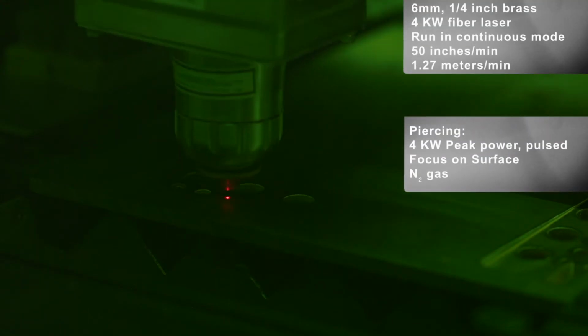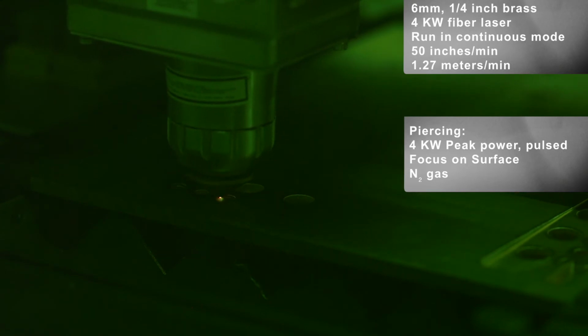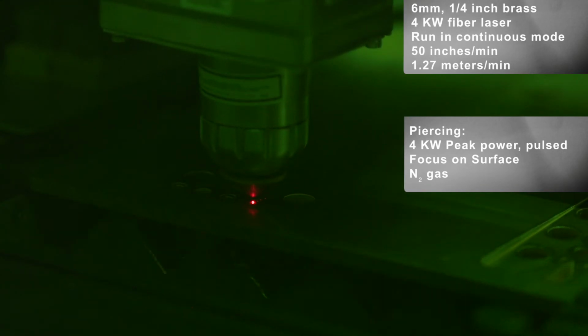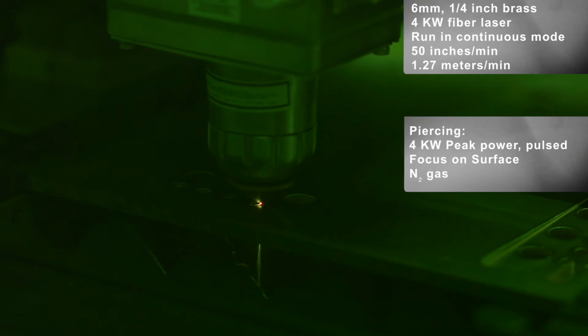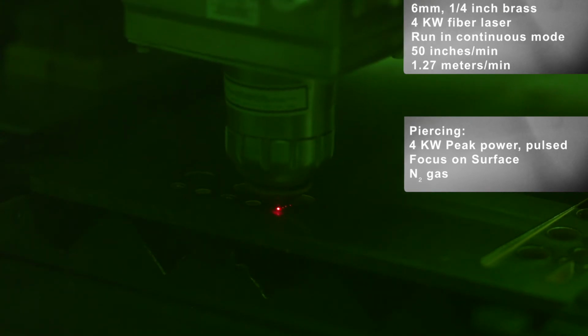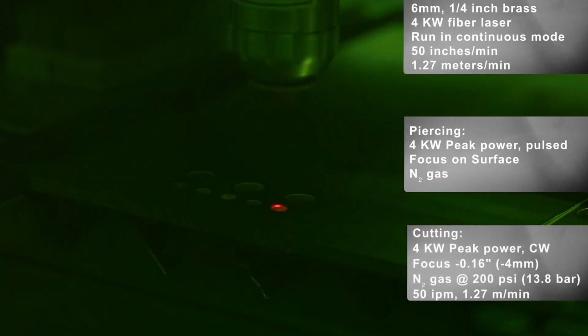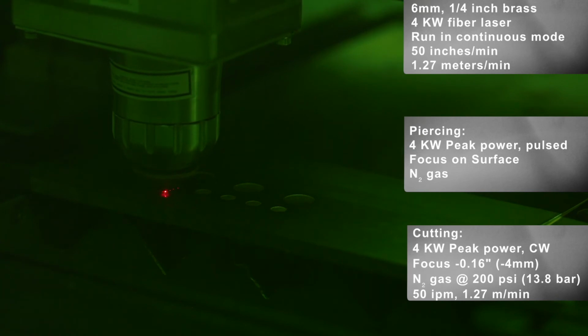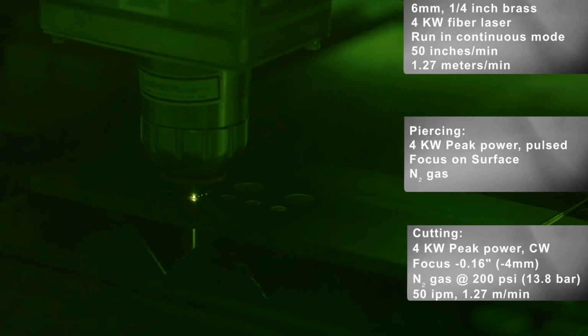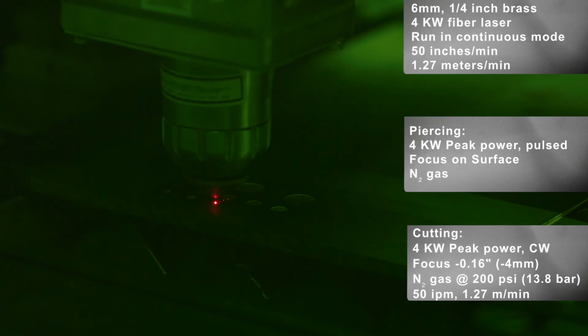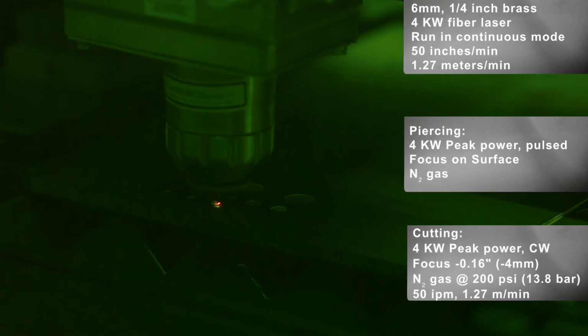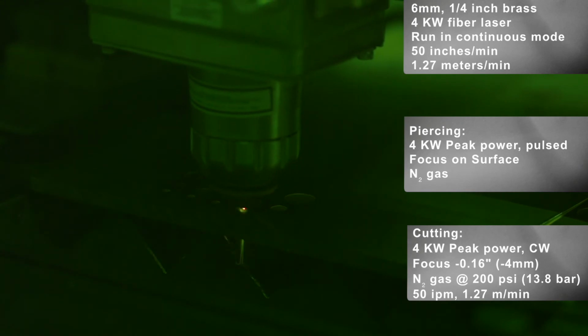In the piercing stage, the material escapes the surface in a particulate form, and the laser is in the pulse mode and drills through the thickness of the material, and then it transitions to cutting. For cutting, to get the good quality, dross-free edge, I need to focus down about 4 millimeters or 0.16 inch into the material.